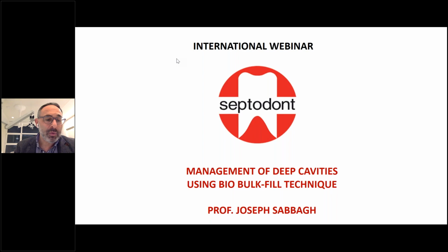So 14 days is for the full setting of Biodentine. Then if you don't have any pain at 14 days, of course, you can move to the final restoration, because basically on the short term, failure of direct pulp capping will occur during the first three weeks. In the literature, it is advised to wait 1.5 months before placing the final restoration. But if at 2 weeks you have no clinical signs, you can go and place your final restoration.